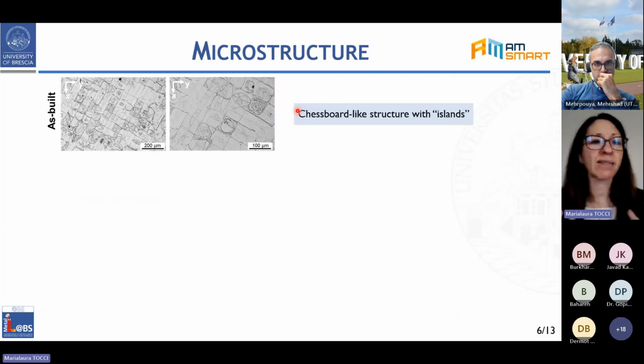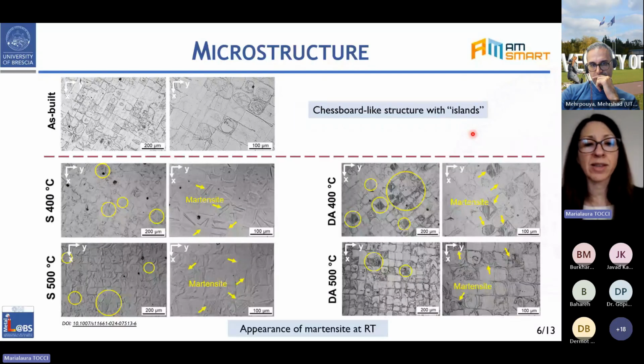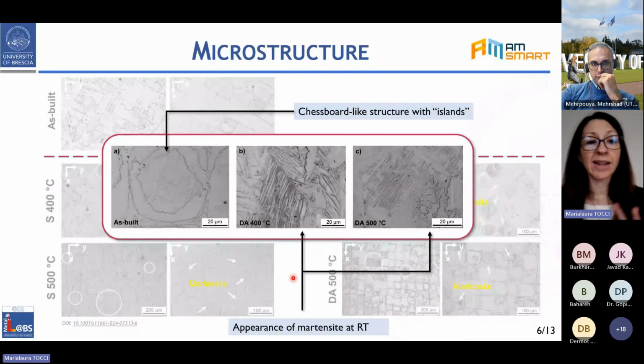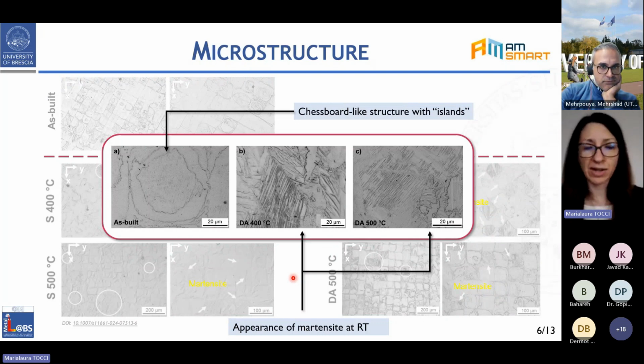Considering instead the microstructure under the as-built condition, we can observe a conventional chessboard-like structure with islands inside the square, and a homogeneous matrix can be identified, while after the heat treatment it was possible to observe the presence of some martensite grains that are highlighted here with yellow circles or arrows, and that can be better appreciated in these images at higher magnification. So according to what we found from the DSC analysis, we have at room temperature after heat treatment both austenite and a limited but still evident presence of martensite.